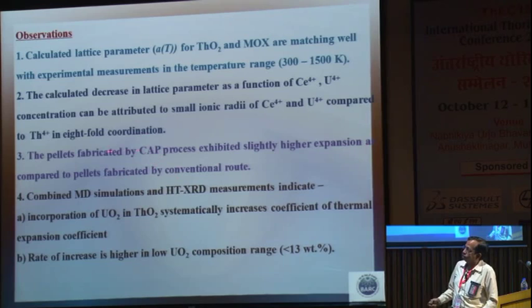And this is a note for the pellet fabricators, that pellet fabrication does have an impact on the thermal properties. Combined MD simulation and HT-XRD measurements indicate that incorporation of uranium in thorium oxide systematically increases the coefficient of thermal expansion. The rate of increase is higher in the low uranium oxide composition range, when it is less than 13%.